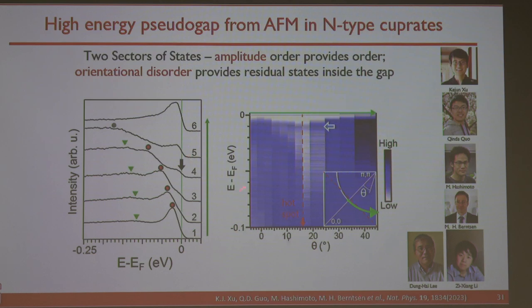And with Dong Hai's work, it turns out you have to consider both the antiferromagnetic amplitude of the magnetic order as well as the orientational fluctuation. And that orientational fluctuation can give you this physics. Just like a superconductor, you have the pairing amplitude and you also have the phase fluctuation. Okay?